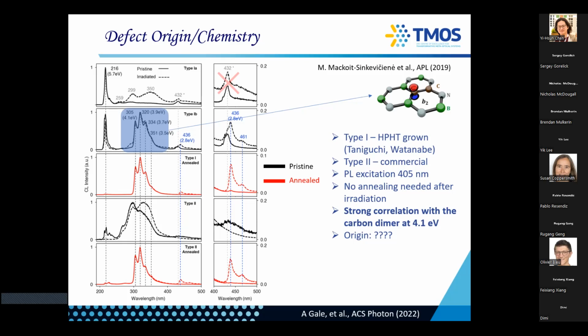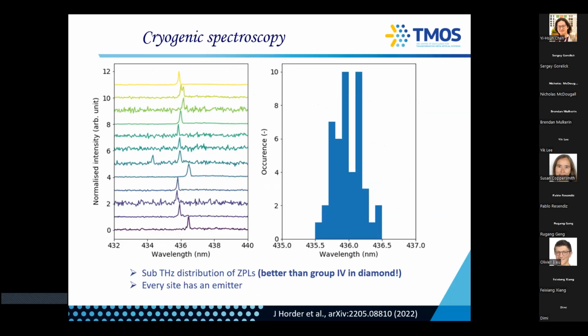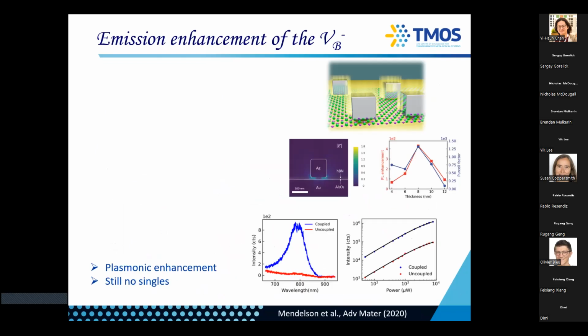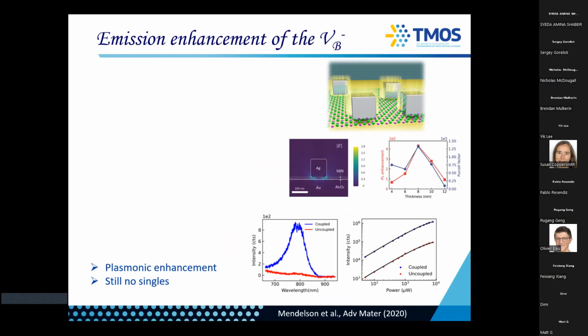Brightness. So the spin defect, you were putting that into optical cavities just to try and see singles, because of how bright it is? Correct. It's very dim. The brightness really depends on how good your optical setup is. But the internal efficiency of this type of defect is probably about 0.5%, probably less even. The reason is as you go closer to the IR, you have more phonons, so you have more non-radiative relaxation. When you put them in cavities, of course they're bright, but they're still not as bright as a single. When we made antennas for the visible emitters, you get basically 10, 15 million counts per second easily on your detector through the collection. So here it is much worse, 100 times worse.